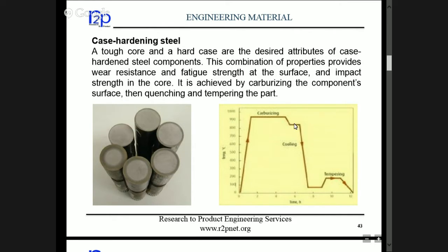Then we again bring the temperature down by 100 degrees, and keep it at that temperature so that homogenization happens. And then we do the quenching. Quenching is preferably done in oil, because water quenching is very severe, so that can result in cracks, micro cracks, which appear on the surface when we grind. So we do sudden quenching, right? And after this whole process of heating and cooling, internally quenching stresses will always be there in the component.